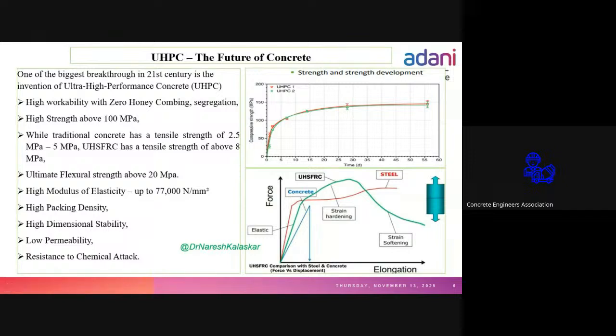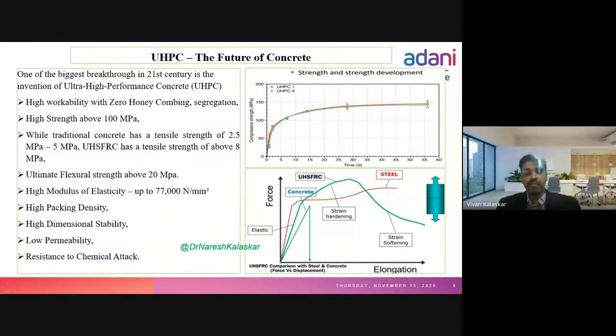Thank you. Okay. The future of the concrete. Now we are in 2025 and we are using up to M80 normal concrete. In the 21st century, ultra high performance concrete will be the future, because of high workability with zero honeycombing. There will be no honeycombing and segregation in UHPC, and minimum compressive strength will be M100. Traditional concrete tensile strength is around 2.5 to 5 MPa, but in ultra high performance concrete, we can get a minimum tensile strength of 8 MPa, ultimate flexural strength of about 20 MPa, and modulus of elasticity of 77,000 N/mm².